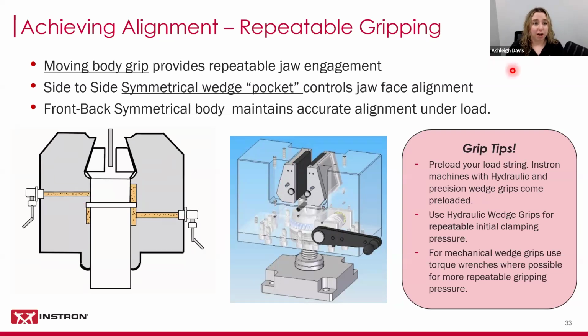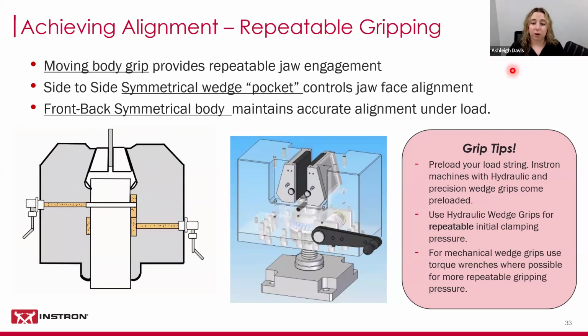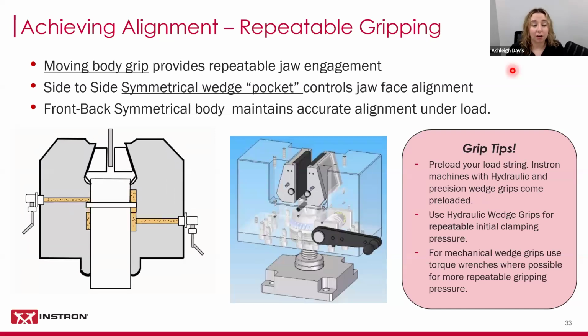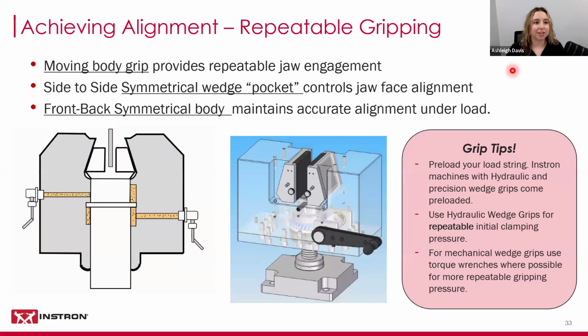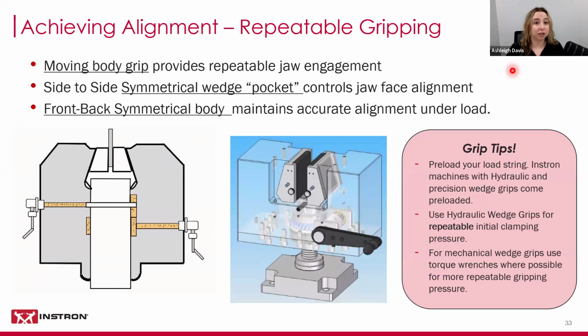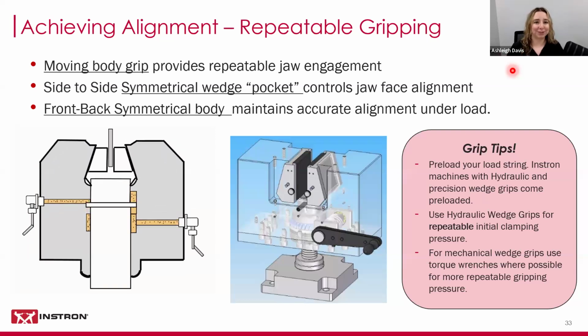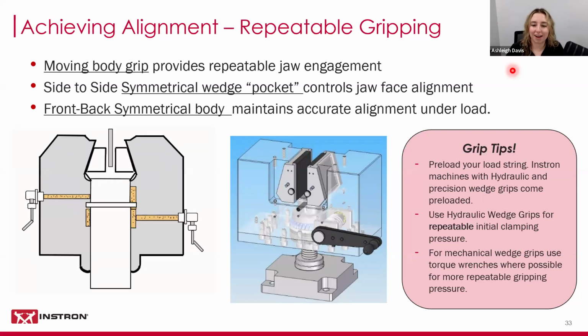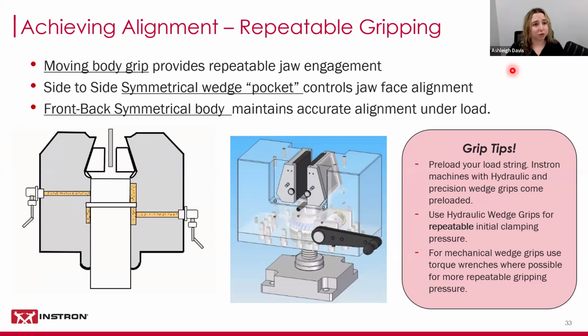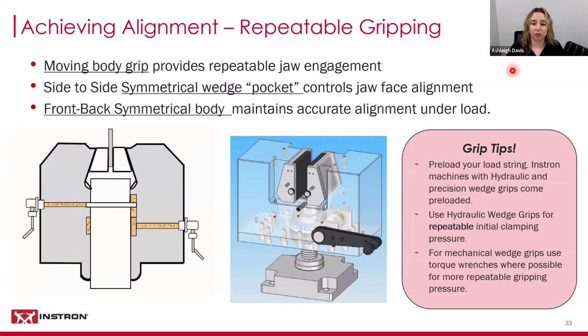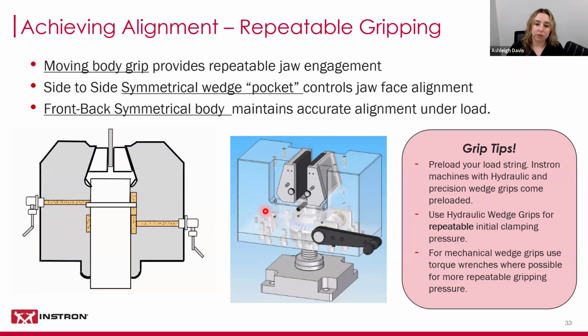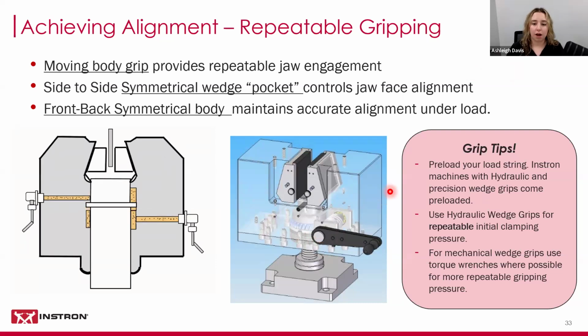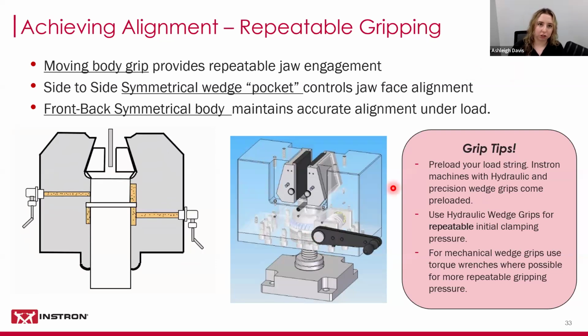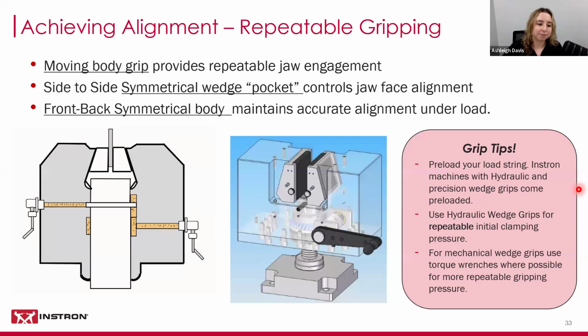Our machines, typically with the hydraulic and precision wedge grips, already come preloaded and should not be removed. We recommend using hydraulic wedge grips as it does provide repeatable initial clamping every single time. In our applications lab, we pretty much exclusively use hydraulic wedge grips. If you are to use mechanical wedge grips, like the precision wedge grips, we do recommend that you use a torque wrench when possible, as you could then have repeatable gripping pressure across different operators.